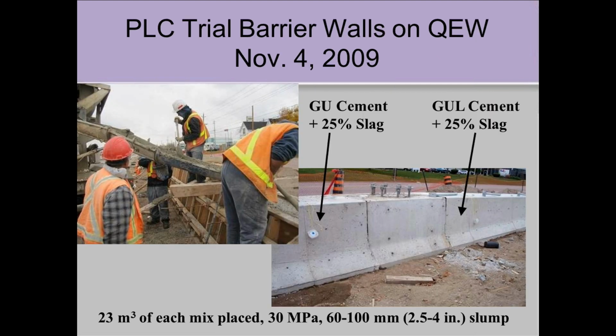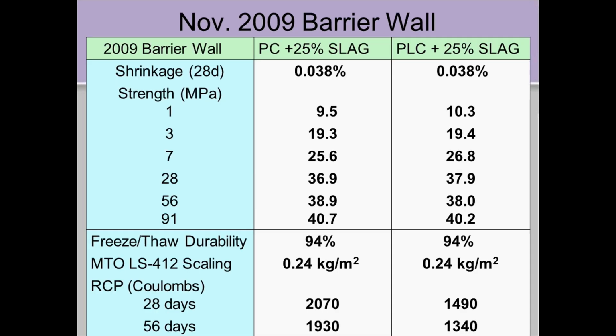And we've been involved not only with the lab work that led up to this, but also with field trials with the MTO, the Highway Department here in Ontario. We did several of them. This is just some barrier walls where we did some trials a few years ago to try and get things going, and we used them together with the traditional slag that's used as the local supplementary material in the Ontario market. And just to look at performance, these concretes with Portland limestone cement, looking at strengths from 1 day through 91 days, they've got equal performance right through.